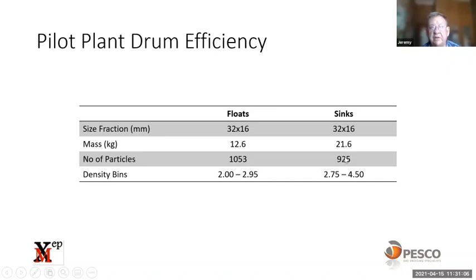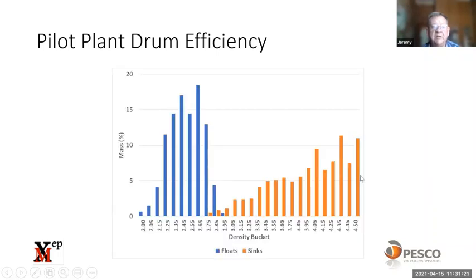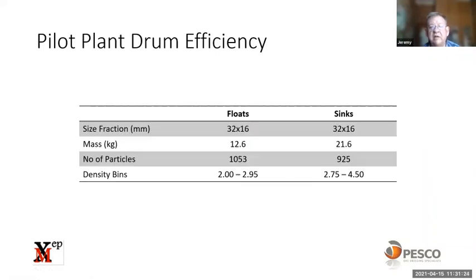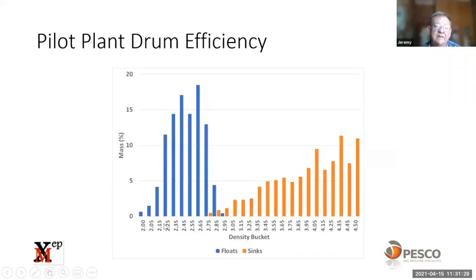And that just shows you the impact of the density of the particles in the floats and sinks, which differ, and the number of particles that are in a certain mass. The floats then occupy density bins from 2 to 2.95, and the sinks from 2.75 up to 4.5. In this case, the total number of particles analyzed was around 2,000. And here's the distribution of the floats and the sinks. The floats are the light densities, the sinks are the higher densities, and around the cut density, you have a bit of misplacement.